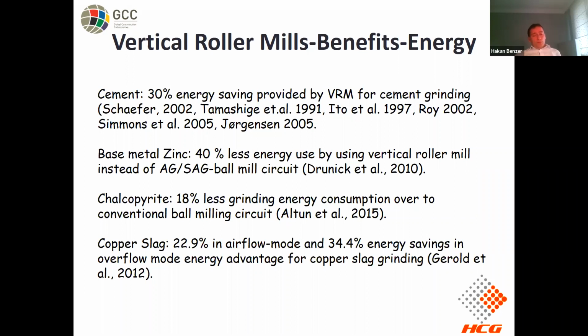What about the metal production? It's been tested for zinc, and it's been observed that, as a comparison to an AG/SAG ball mill, it consumes 40% less energy with the vertical roller mill.